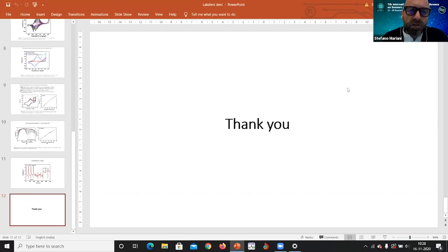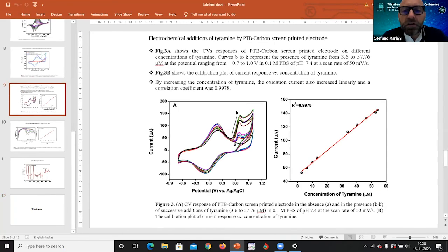Looking at the calibration plots you provided, we see that a linear fit is always very good, because I see R squared is always very close to 1. So are the results coming from a single test, or from repeated tests? Multi-test. I didn't add the error bar. Yes, that was my question. Yes, in fact, I should add it, but I didn't think to add it before. The test is not just a single one. I made it 3 to 4 times, and then I concluded it and put the calibration plot. Later for the publication, I could add the error bar. Okay, thanks.